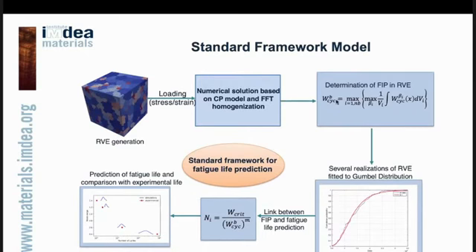Here we use energy based fatigue indicator parameters. Since fatigue is a stochastic phenomenon, we need several realizations of the RVE to take this probability into consideration. We will fit the Gumbel distribution. Then we make a link between the FIP that we have and the fatigue life, and then finally we predict the fatigue life.